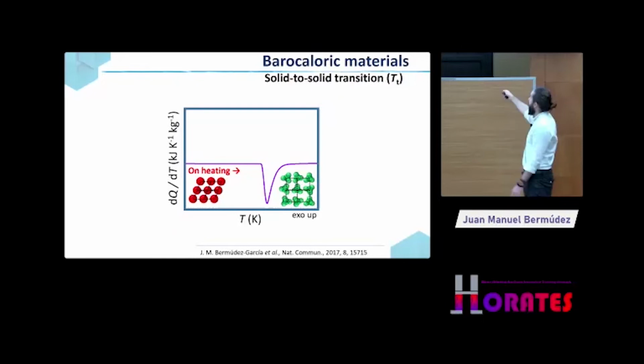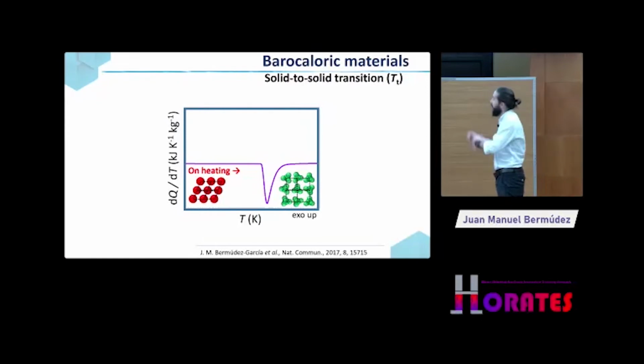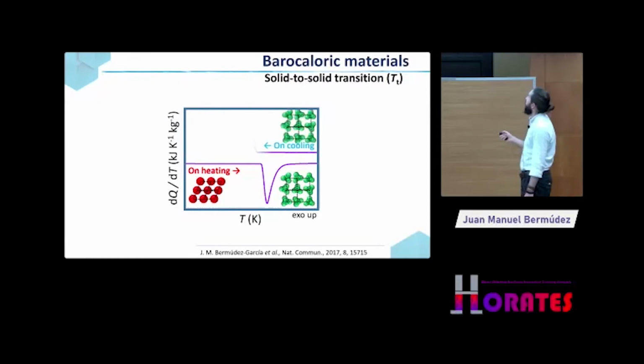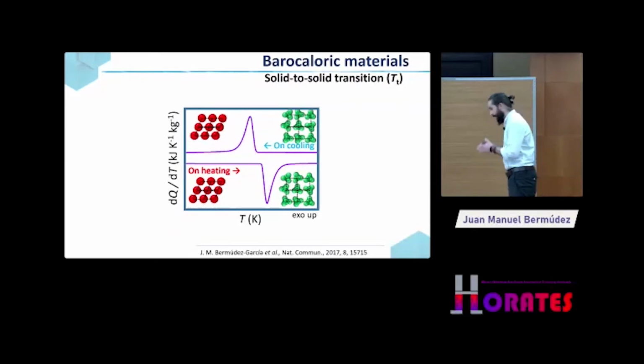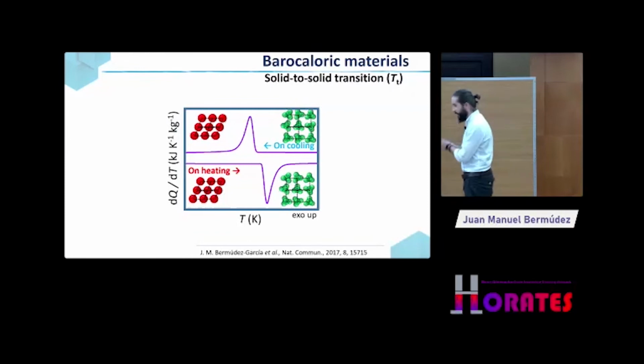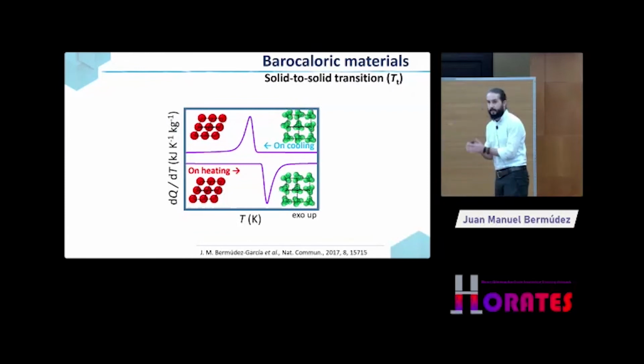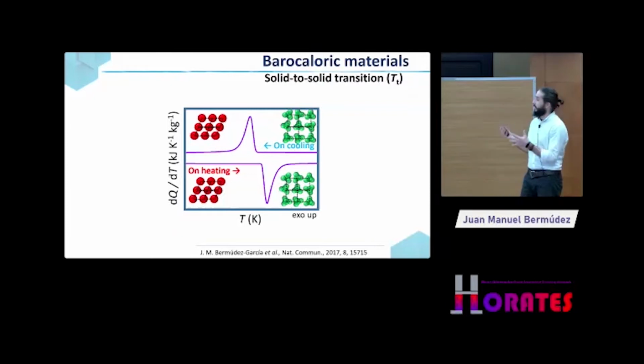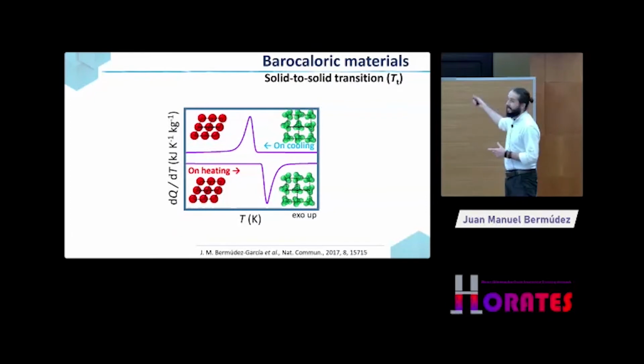And then from this peak, you do the integration and you can calculate the latent heat or the enthalpy change associated to this transition, meaning the heat that is absorbed during the transition. And then you can know as well the transition temperature, which is the temperature at which this transition takes place. And you can reverse the transition and you obtain the information from the high temperature phase to the low temperature phase. So that will be the characterization of your material under ambient pressure and as a function of the temperature. But what we would like to do is to study the material as a function of pressure, because we want to know what is this heat absorbed or released when you apply the pressure, okay?